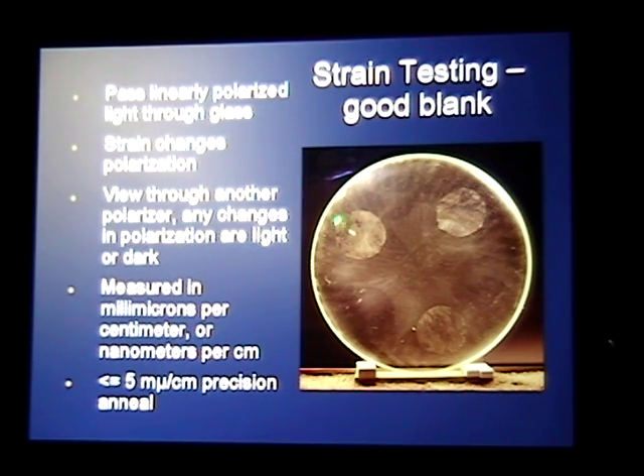Now, on the back of the mirror, we have what's left of a giant blob of adhesive here. We have some swirl patterns from the actual machining of the back flat. But generally, the illumination of this glass is pretty evenly gray, roughly. We don't see any bright or dark parts jumping out. So the anneal of this glass is quite good. This is something that generally can only be done with a coating off of the mirror. So whenever I do a refigure job or whenever I buy glass, I check the anneal of it right off the bat to make sure I'm not working with a bunch of springs internally in the glass.